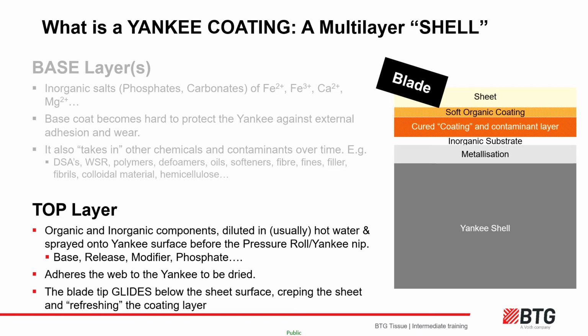Coating itself establishes and undergoes several disruptions during machine operation. For example, creping blade changes strip coating back as a new sharp blade removes more of the cured coating layer than the previous worn blade was doing. Chemical cleaning of felts or system cleans or wash-ups, even high sheet moisture, can wash coating off the Yankee cylinder. Additionally, changes in process conditions, chemical additives, water usage can alter the concentration of contaminants impacting the organic coating. It is important to understand the process and proactively manage and centerline wet end, chemical add-ons, blade management and all other influencing factors to keep coating as stable as possible with as few disruptions as possible.